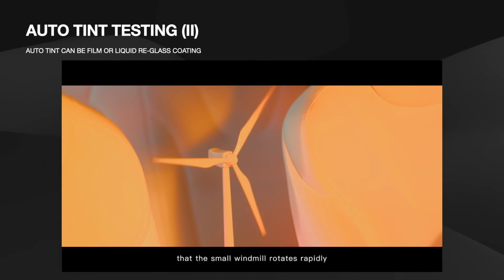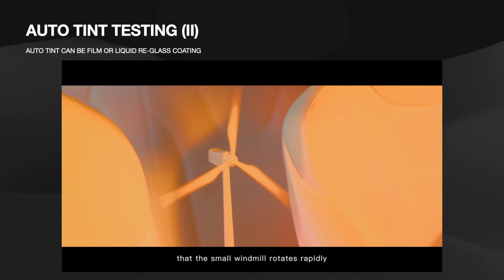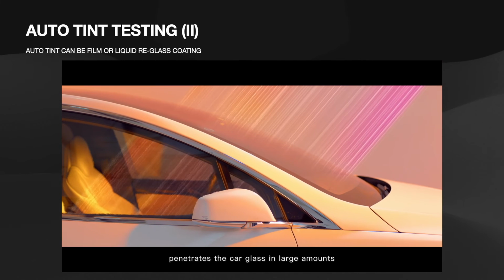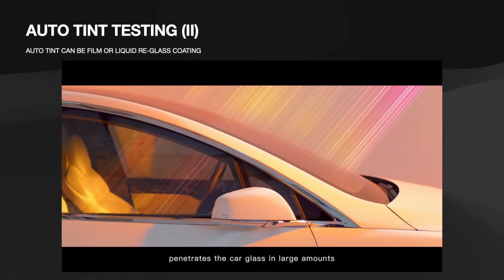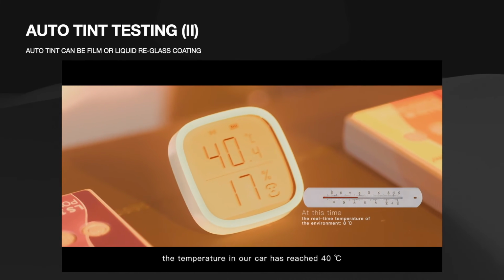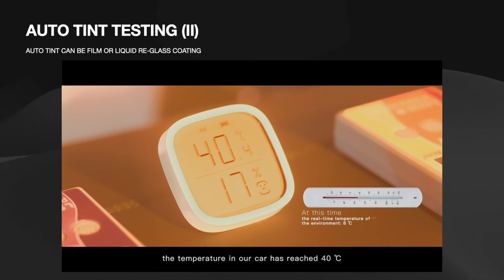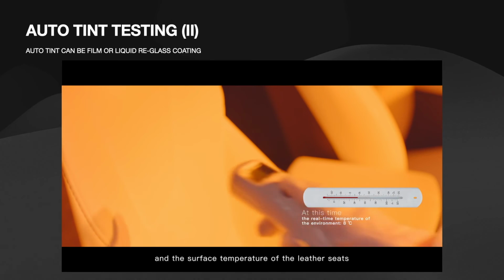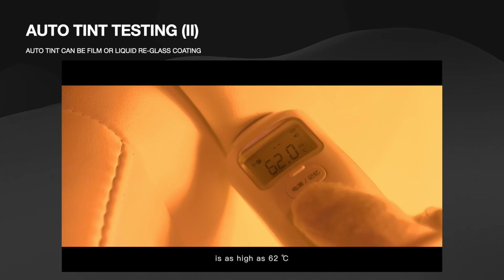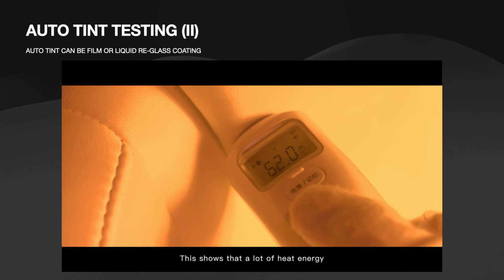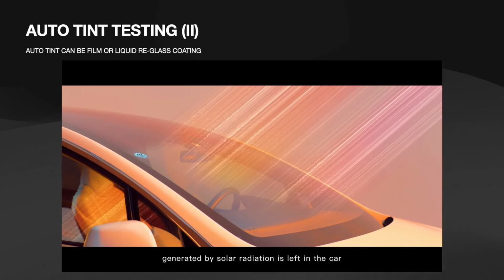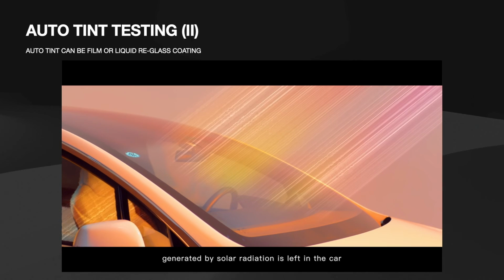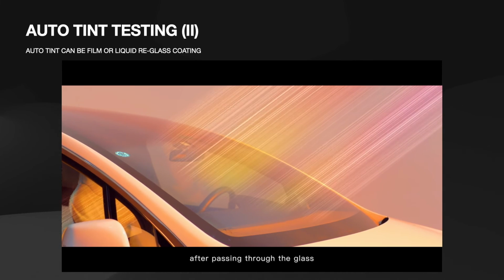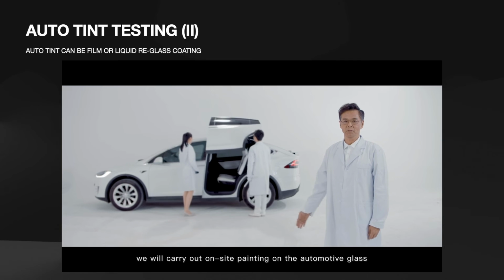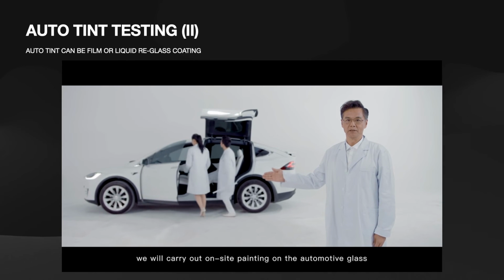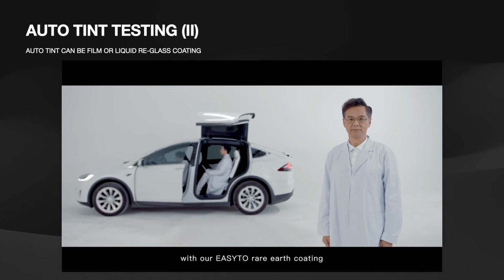It can be seen that the small windmill rotates rapidly and the radiant heat of the sun penetrates the car glass in large amounts. 10 minutes later, the temperature in our car has reached 40 degrees Celsius, and the surface temperature of the leather seats is as high as 62 degrees Celsius. This shows that a lot of heat energy generated by solar radiation is left in the car after passing through the glass. Now, we will carry out an on-site painting on the automotive glass with our EASYTO rare earth coating.